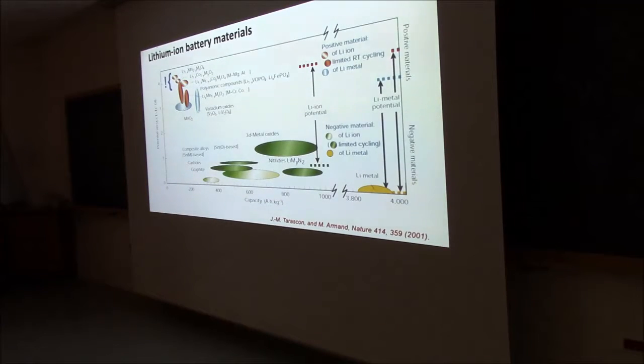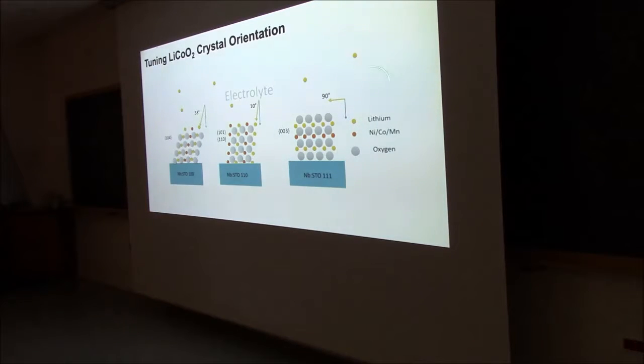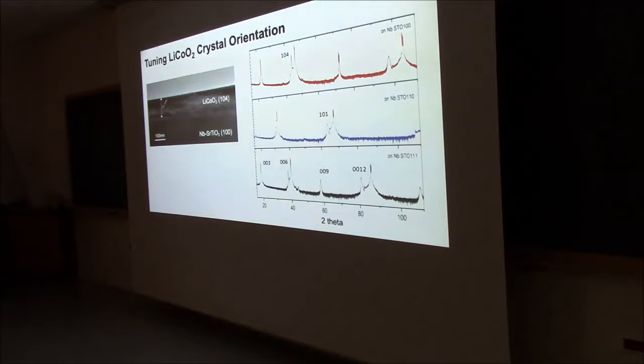We also looked, and I want to show this quickly, into the nanomaterial lithium cobalt oxide. Lithium cobalt oxide has this layered structure, you can see here. If you put it on doped STO, on the 101, the layering is like this, and it's difficult for the lithium to get out. If you put it on different orientations, you can align these planes so that the lithium, in the simple understanding, would be able to move out much more easily. In here, if we take a 100 substrate, it would be around a 104 orientation. So we grow these thin films, and you can see that they are nicely oriented with a specific orientation, and this indeed is the 104 in this lithium cobalt oxide.